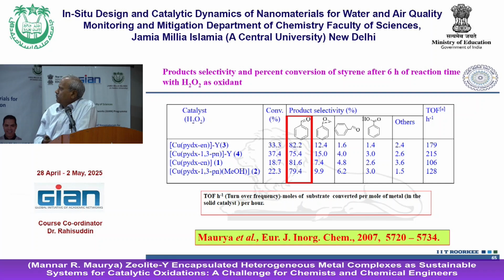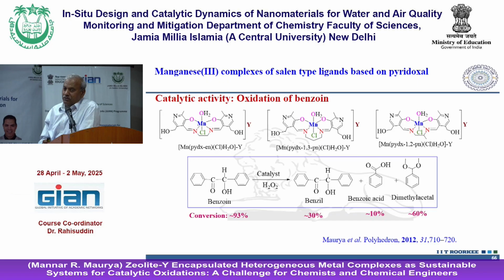Okay, with manganese, just to see if the metal change helps. So we have done some reaction with the benzoin, and the major product is actually dimethyl acetal. After breaking the bond, benzil is 30%, benzoic acid 10%, and dimethyl acetal is almost 60%. But conversion is good, at least we can say that. So this can be done, and benzil is not a bad product and not bad in yield, and this is useful in other organic reactions.